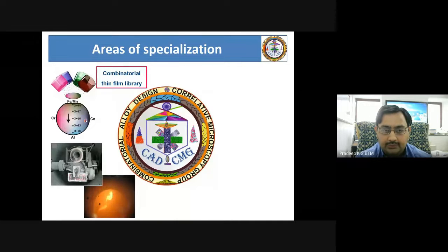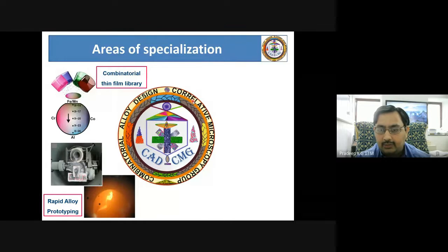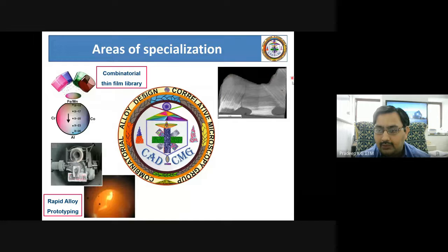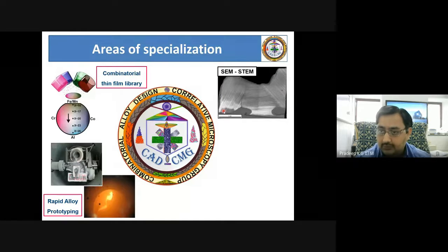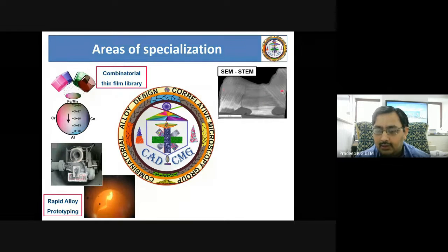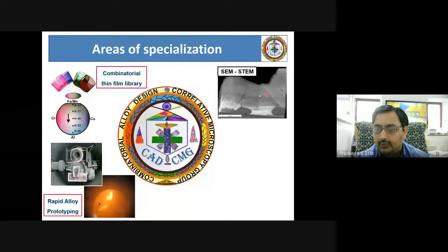So when we produce materials of this nature, where there is a strong chemical variation as a function of production, we need adequate techniques to characterize these materials at multiple length scales. That means we do, on the other hand, what is called a correlative microscopy approach, where you get a microstructure like this, for example, in a scanning electron microscope using, for example, a scanning transmission mode, where you can look at the scale bar and realize these are all nanoscale features of mechanical twins that you can see in a microstructure. But right now, looking into this image, it is only dark and white contrast. There is nothing much we can talk about what is the crystallographic orientation of these twins, or what is the identification of the phases present inside.